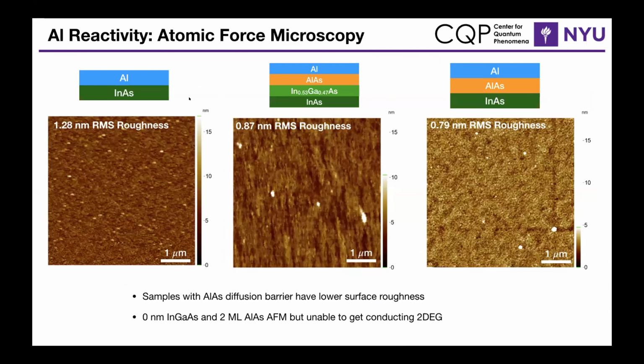And we've also conducted AFM studies of this, and we've varied the different kinds of barriers in between the aluminum and indium arsenide layers. So with the sample of aluminum directly on indium arsenide, you have an RMS roughness of about 1.3 nanometers. Whereas when you introduce these intermediate layers, you can lower the RMS roughness to 0.9 nanometers and 0.8 nanometers, where the best sample is shown on the right with the aluminum on indium arsenide with this intermediate aluminum arsenide layer.